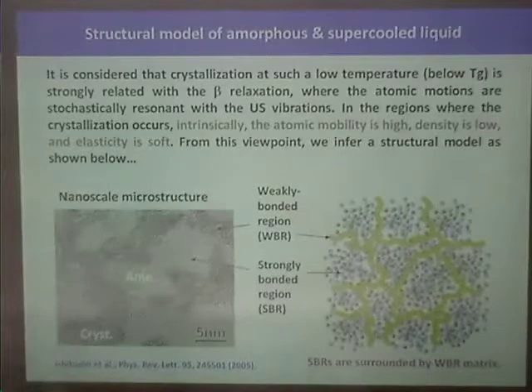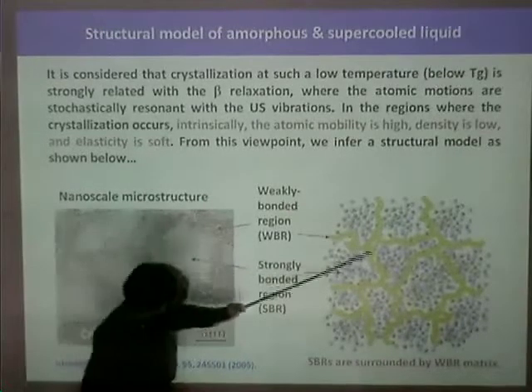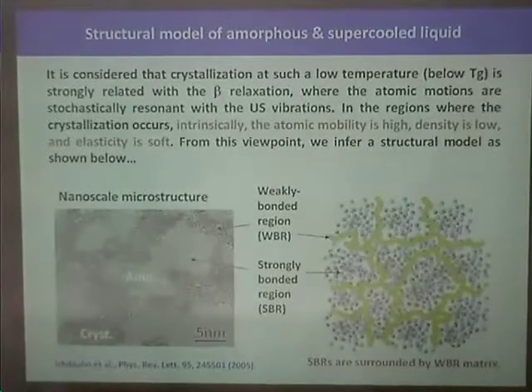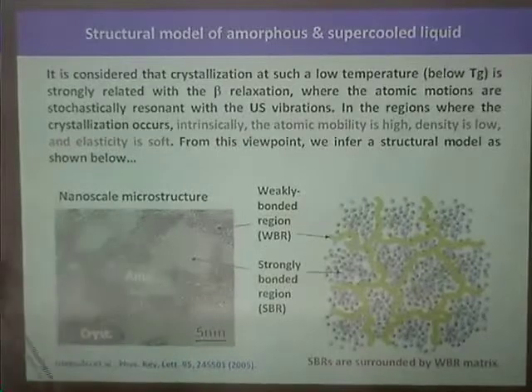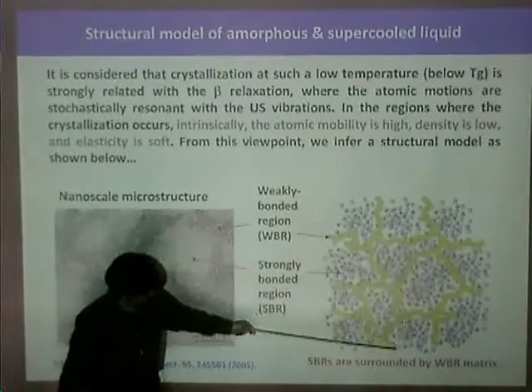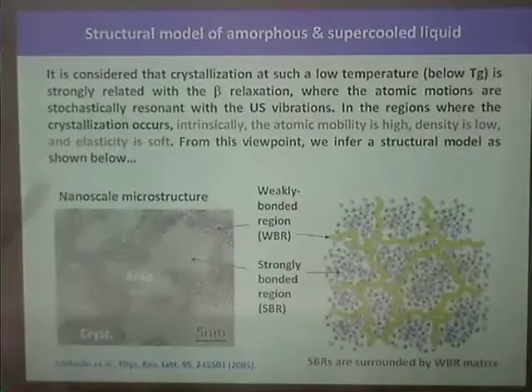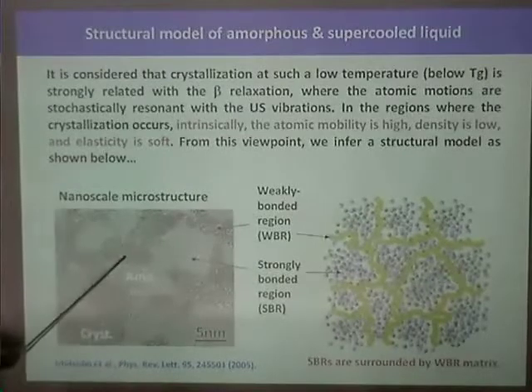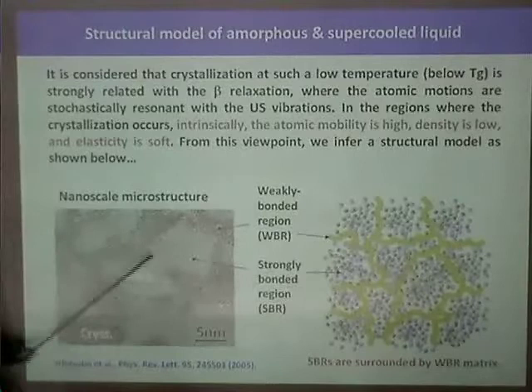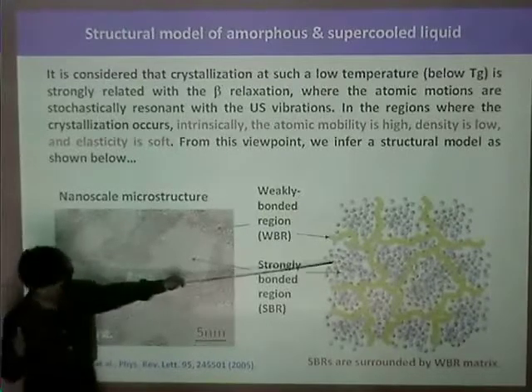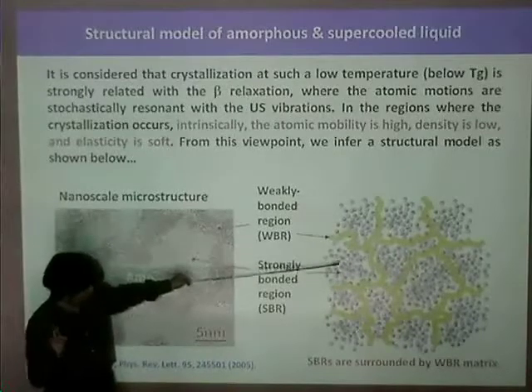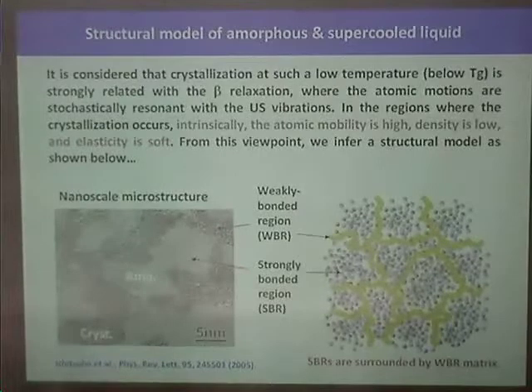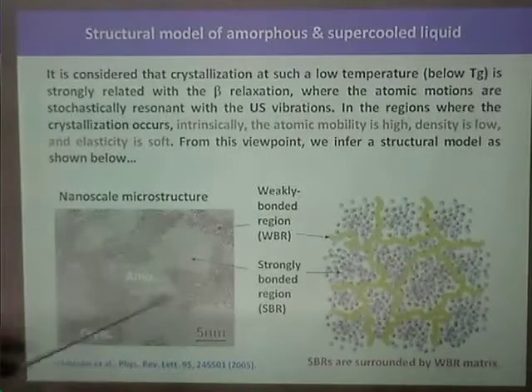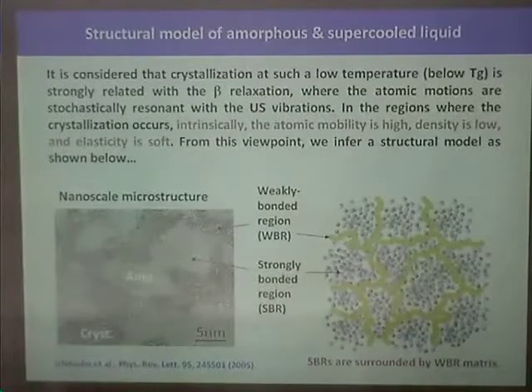So probably percolate only. Percolation structure is maybe not essential, but probably. This can't be directly derived from this structure. This is just an intuitive image based on the thermodynamic behavior. But it's a misleading image in the sense that you draw it as percolating, and there's nothing about the phenomenon that shows that.